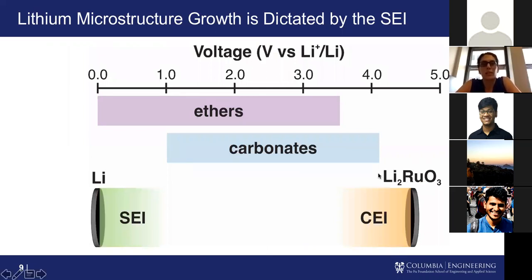This is a diagram showing how a lithium ion battery essentially operates. You have your anode, which in our case is lithium metal, and then you have some cathode material. This is just a common example, but this could really be any type of material. And this x-axis here is just showing the voltage difference between these two materials. Lithium metal or graphite, which is more commonly used in commercial lithium ion batteries, shows up somewhere around 0 volts. And then you have your cathode material that's going to show up somewhere around 4.2 to 4.5 volts up here. So you have this separation in the potential between your anode and your cathode, and that's what allows the battery to function in the first place.